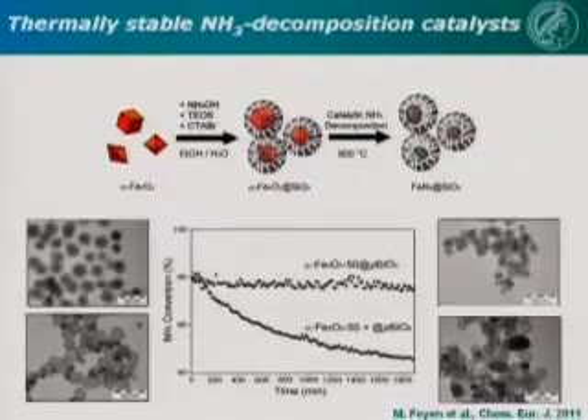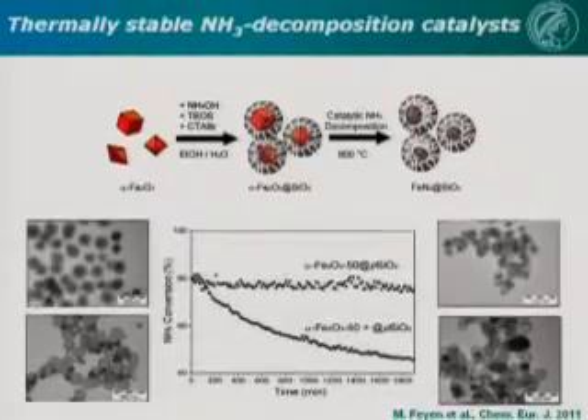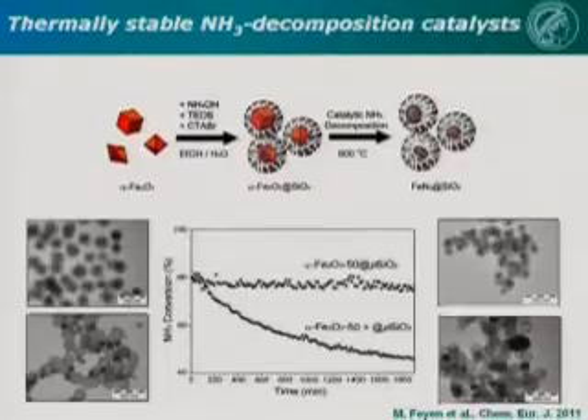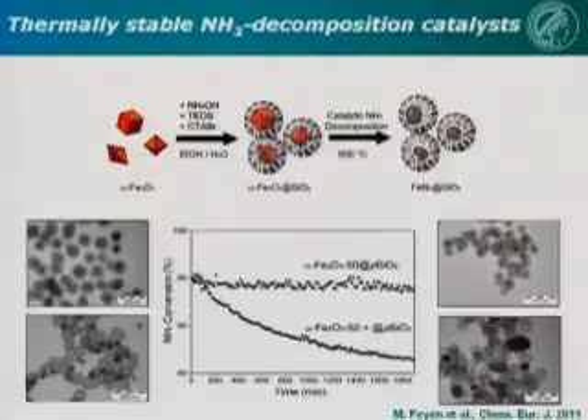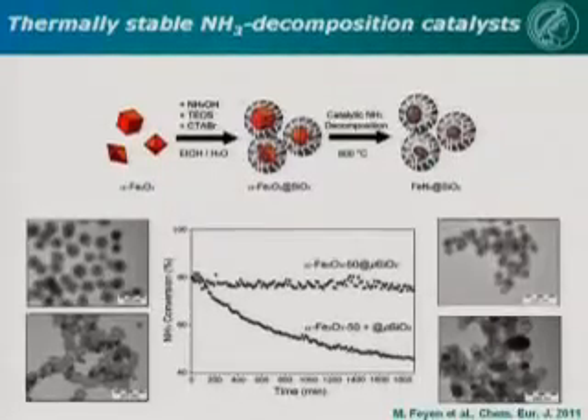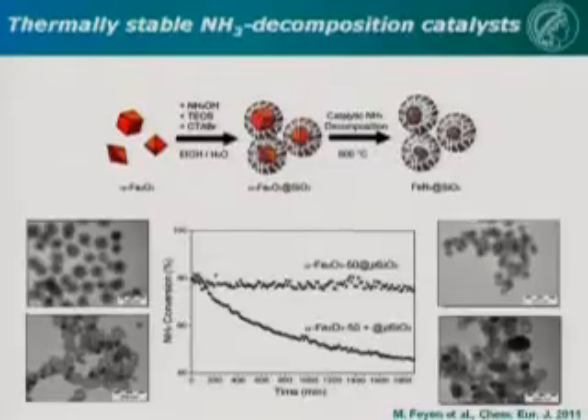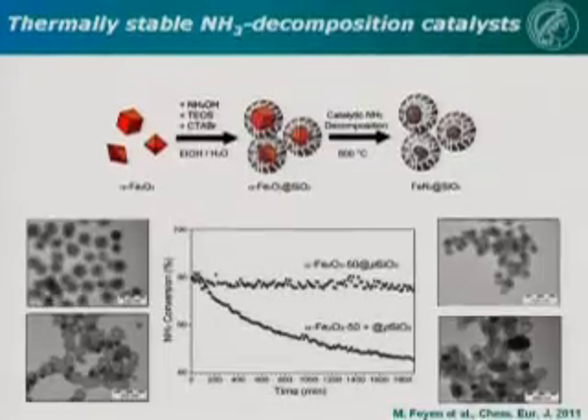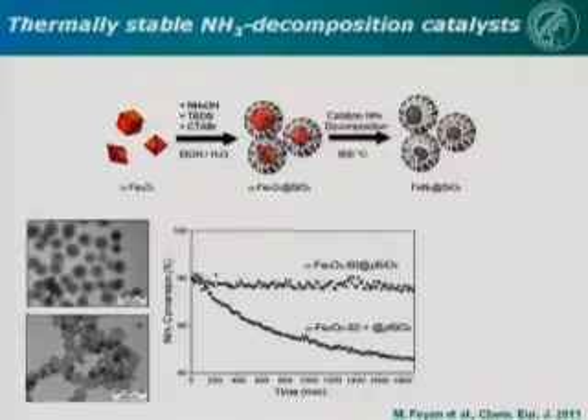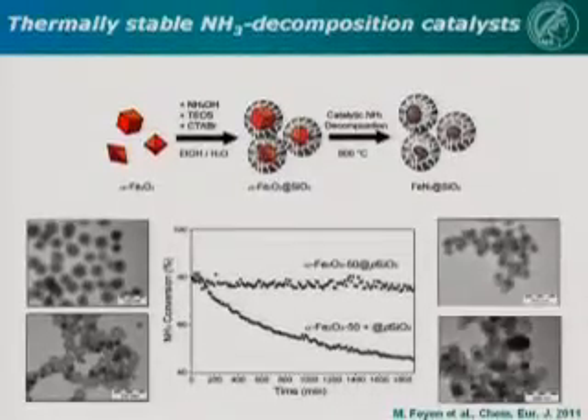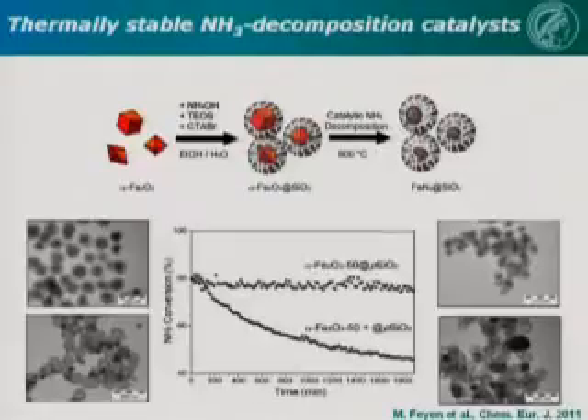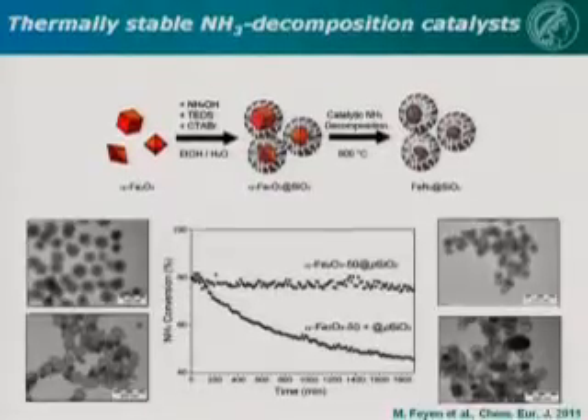And if you look at what happens after reaction, well, those of you working with catalysts can imagine what would happen. This catalyst hasn't changed. The iron oxide is still encapsulated by the porous silica, but here we have big blobs of iron nitride, or oxided. If you take it out of the reactor, you have this oxide surface coverage, oxided iron nitride catalyst. So this is the reason why you lose activity here while these protected ones retain their activity. We will see similar examples also further in the talk.